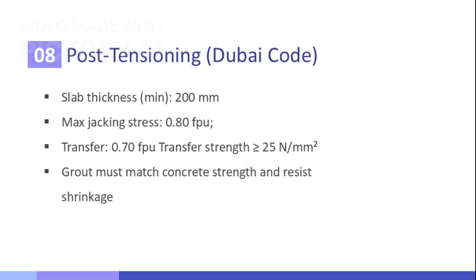Then, we have the transfer strength. This is the stress when the tendon force is transferred to the concrete. It should be limited to 70% of fpu, and at that point, the concrete must have gained at least 25 newtons per square millimeter strength to safely handle the stress. Finally, we can't ignore the grout. It's used to bond the tendons and protect against corrosion. It must match the strength of the concrete and must also resist shrinkage, or we risk creating voids and weakening the bond. These values are critical to ensuring safety and durability in post-tension slabs, especially under Dubai's specific construction guidelines.